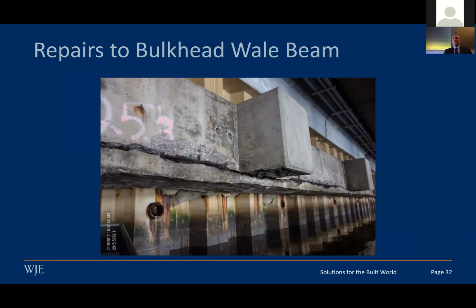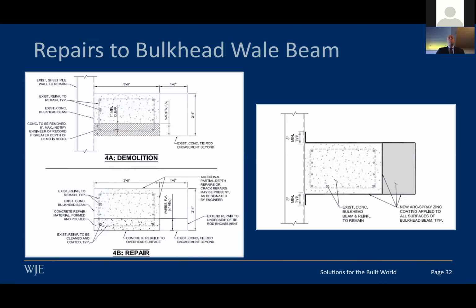This is a picture of the bulkhead wale beam, and this is where we saw pretty significant deterioration in that bottom mat of steel. So you can see that crack, the lamination that's occurring there. As a result, we did the concrete repair that we talked about. That's what the pictures on the left are, to remove that unsound concrete and cast it back.